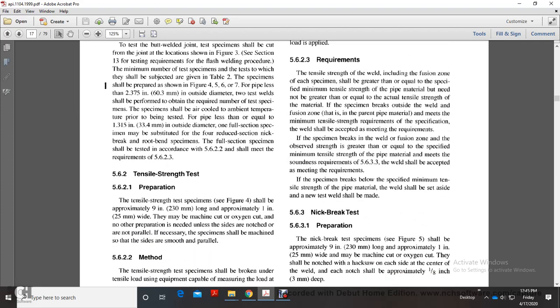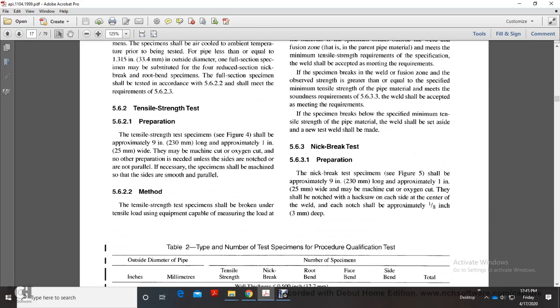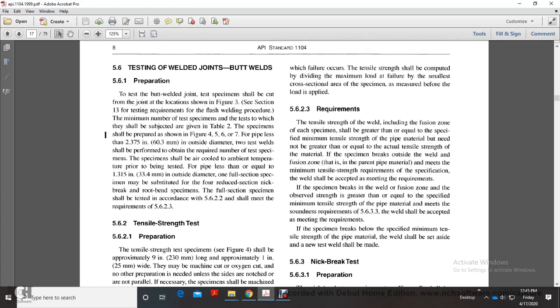5.6.2 Tensile strength test. 5.6.2.1 Preparation. The tensile strength test specimen, Figure 4, shall be approximately 9 inches long and approximately 1 inch wide. They may be machine cut or oxygen cut. No other preparation is needed unless the sides are not smooth and parallel, in which case the specimen shall be machined so that the sides are smooth and parallel. 5.6.2.2 Method. The tensile strength test specimen shall be broken under tensile load on equipment capable of measuring the load at which failure occurs. Tensile strength shall be computed by dividing the maximum load at failure by the smallest cross-sectional area of the specimen, measured before the load is applied.